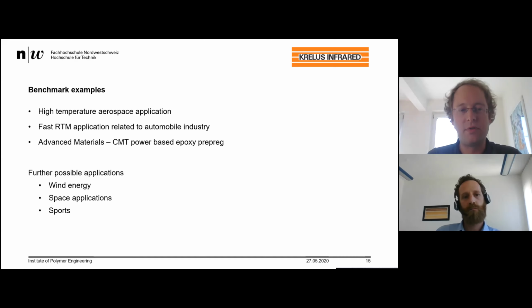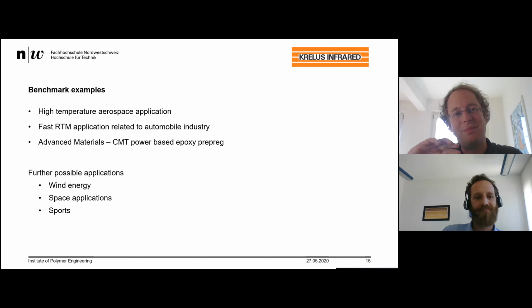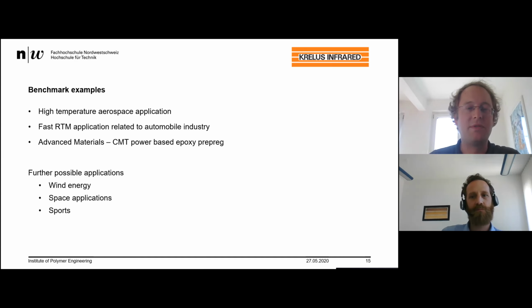So we applied an infusion process with a really reactive resin system, which is normally used in high pressure RTM, so a system which reacts in 2 minutes. And then I want to show you one additional trial which we have done with the company CMT. So it's a provider for powder-based epoxy prepreg systems, and there we applied an advanced control, a nice demonstration of what is possible to follow a complex curing profile. And further possible applications, of course, are wind energy or space or sports and so on.